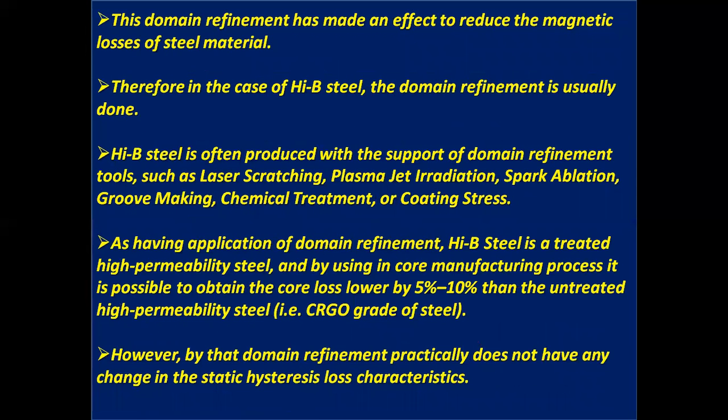This domain refinement has the effect of reducing the magnetic losses of steel material. Therefore, in the case of HIB steel, domain refinement is usually done. HIB steel is often produced with the support of domain refinement tools such as laser scratching, plasma jet irradiation, spark ablation, groove mark making, chemical treatment, or coating stress. As an application of domain refinement,